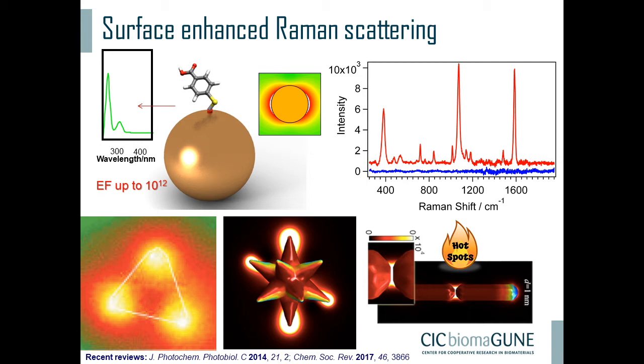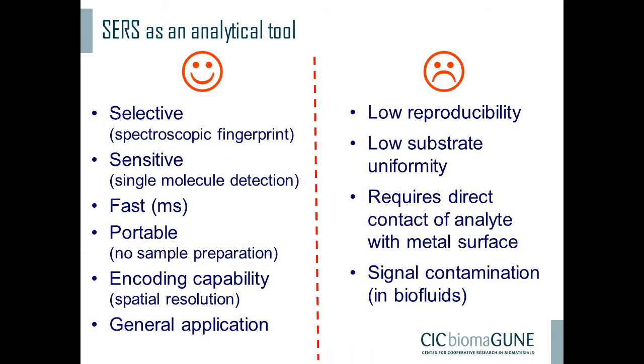The problem is, if you do it that way, that it will be random. And so you will never know exactly how much you're amplifying at each part of the aggregates. And this is why I have my own list of advantages and drawbacks that, in my opinion, are the major reasons why surface-enhanced Raman scattering is not yet in the clinic or in the market. There are many reasons why it should be, and I already mentioned a few, but there are also reasons why it is not, and they are related to the reproducibility of the substrates, the uniformity within the same substrate. As I said, if you're aggregating particles on top of a substrate, the organization of the particles can be completely different at different spots, and then the enhancement will be completely different.